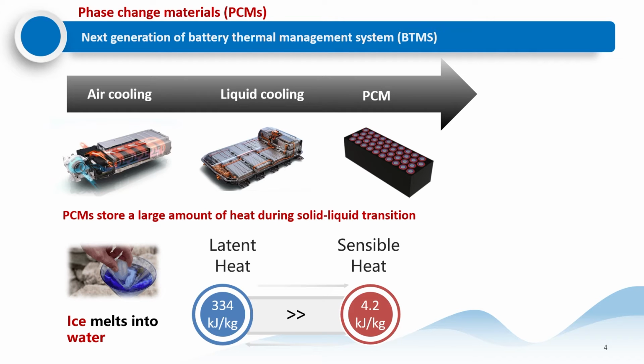PCM cooling systems is actually a system that uses the PCM, which is a material that can store a large amount of heat during a solid to liquid phase transition. For example, when ice melts into water, they absorb a lot of heat inside it. We take it as the latent heat. For example, 1 kilogram of ice can absorb 334 kilojoules of heat, which is larger than its specific heat, which we call the sensible heat, which is only about 4.2 kilojoules. So if we use PCMs to cool down the battery, we can use the very large latent heat to cool it down and maintain a constant temperature. We call it the phase change temperature.